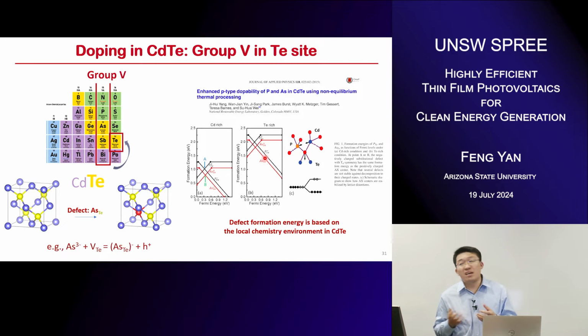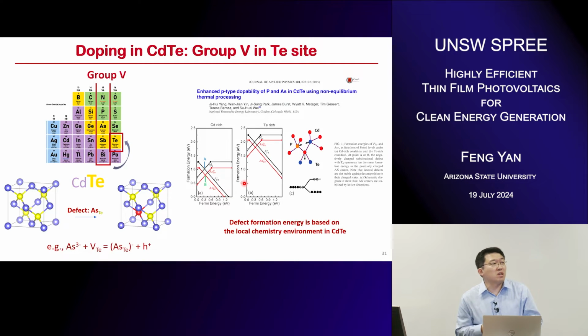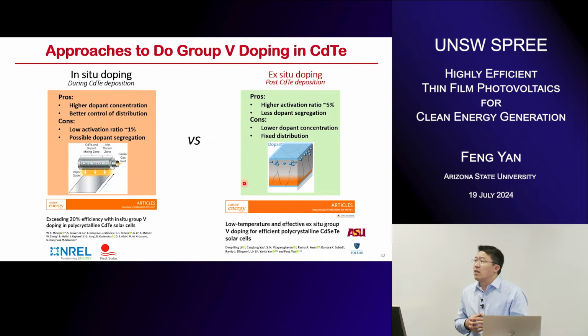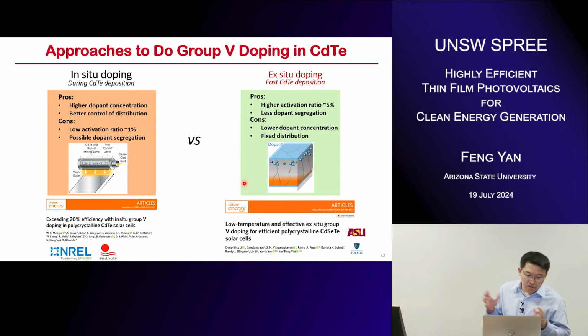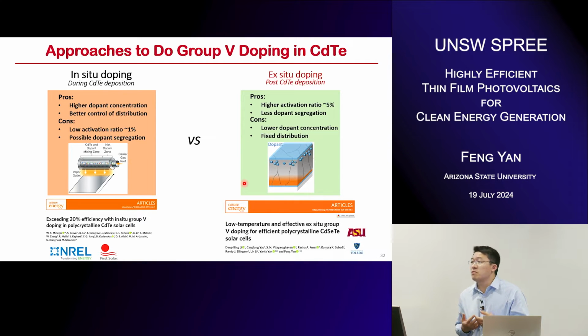Group 5 doping gives another chance to occupy the telluride site using nitrogen, phosphorus, arsenic, or even antimony. They have more freedom to tailor the carrier environment. For example, theoretical predictions also give us guidelines on how to generate this group 5 doping. And in the past roughly 10 years, we cracked the way to achieve group 5 doping. For example, First Solar and Univ. of Toledo are working on in situ doping. Why do we call it in situ? Because these dopants can be introduced during the film deposition using vapor transport deposition or other ways.